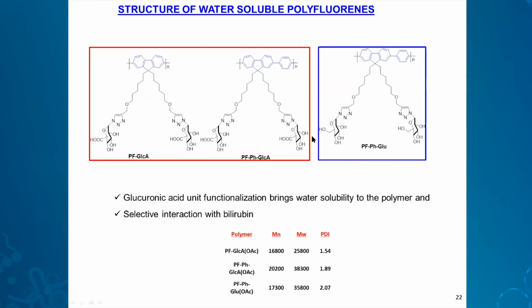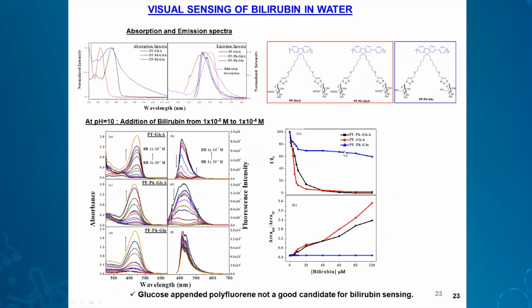So these are the polymers that we designed. The synthesis is not shown here for want of time. We made two polymers. This is polyfluorene, only fluorene in the backbone. Here it is a copolymer with the phenyl ring, and this is the glucuronic acid. And as a reference molecule, we made this polymer with glucose also. So if water solubility is the only reason, whether this will also do the same job of detection of bilirubin. And summarized here are our studies with this system.